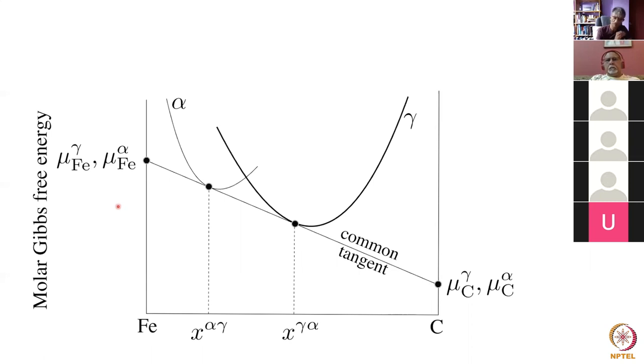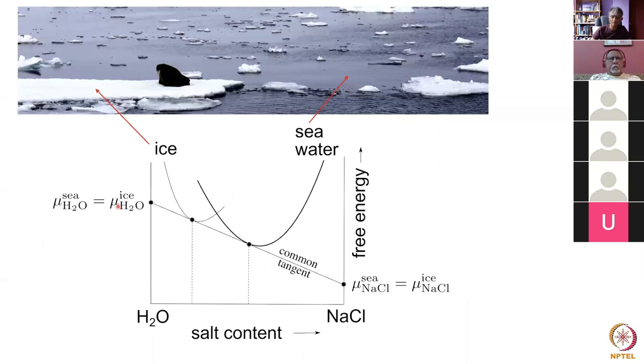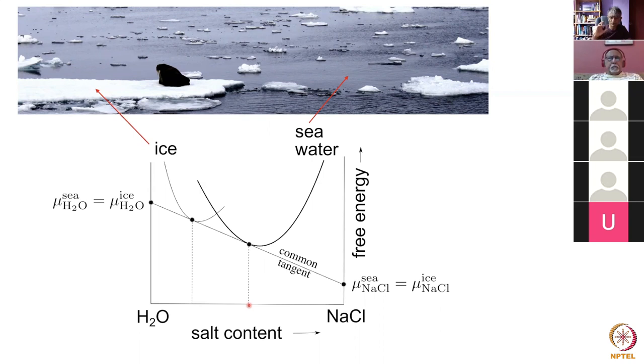The common tangent allows us to obtain the equilibrium compositions once we know the free energy functions. For example, when ice freezes from seawater it turns out to be pure water while the seawater remains rich in salt. The reason is that the free energy of sodium chloride in the sea is the same as in ice, and similarly for water molecules — even though the ice is pure and the seawater is not. There is no tendency for salt to transfer from water to ice; the ice can grow while rejecting salt into the water, but at equilibrium there is no redistribution of solute.